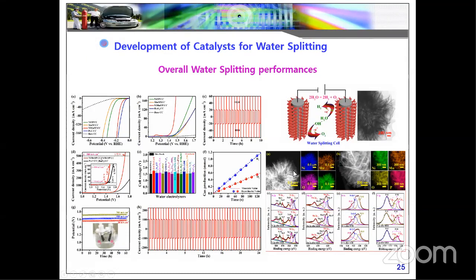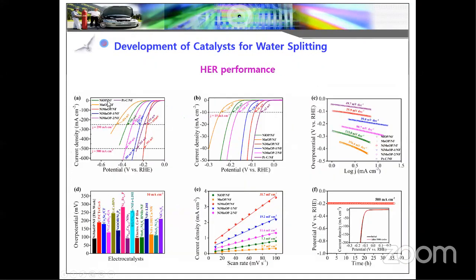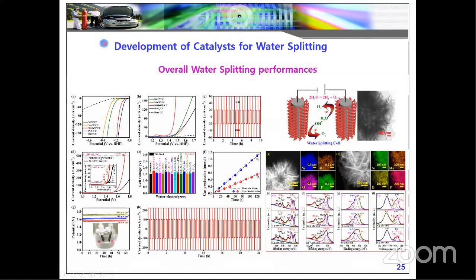Before that, I forgot to mention one thing. You can see nickel foam here, because we are growing the materials over nickel foam, and we performed all characterizations on it. But for the reversibility test, the nickel foam also acts as a catalyst. In order to avoid this issue, we also grew the material on carbon cloth substrates. On carbon cloth, you can see almost similar overpotential is observed. We then performed HER and OER at lower current density for the reversibility. You can see the reversibility is maintained in the 3 electrode system. And we are also comparing our catalyst to the commercially available catalyst.